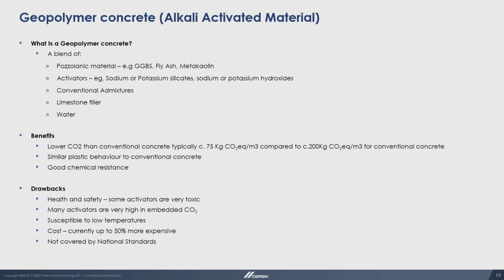There are some drawbacks. Health and safety wise, the chemicals are very difficult to handle, and you've got to be very careful with those. As I said, the activator is very high in CO2, and some of the formulations are susceptible to low temperatures. Bearing in mind, particularly if you've got effectively 100% slag as your material, then that can be sensitive to lower temperatures. Current cost, they're more expensive than conventional concretes.